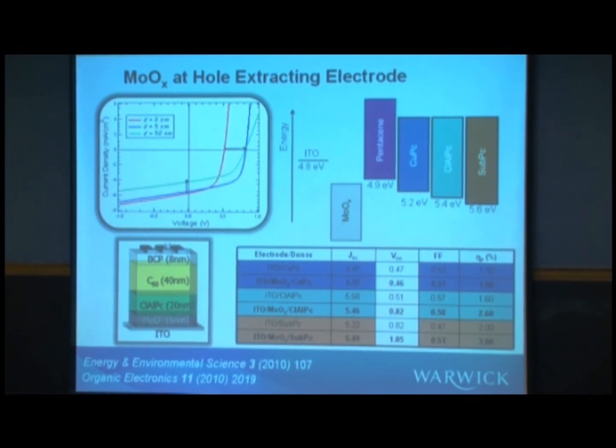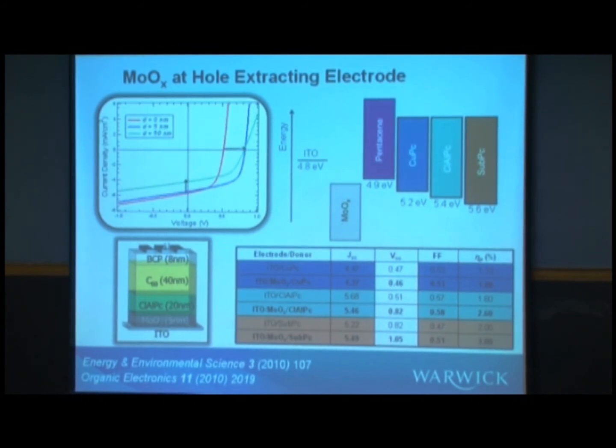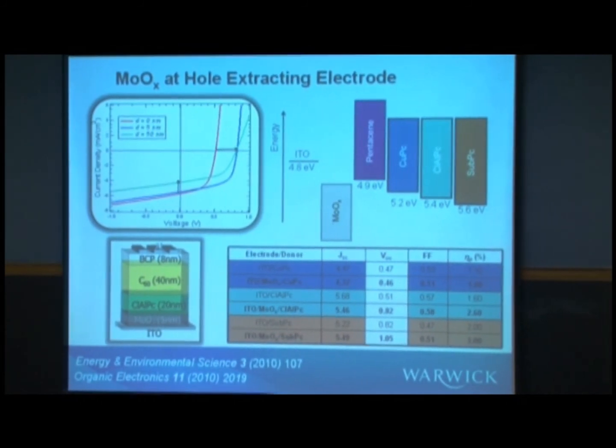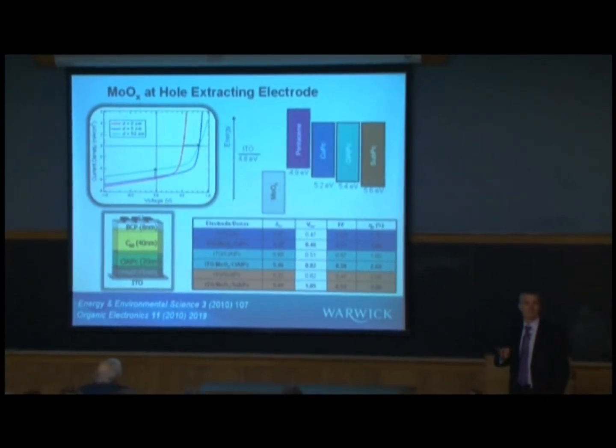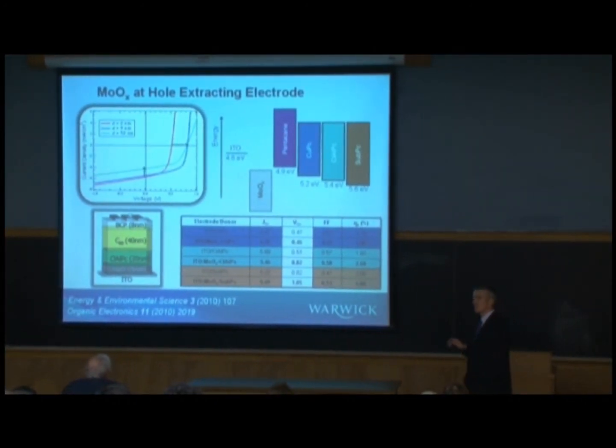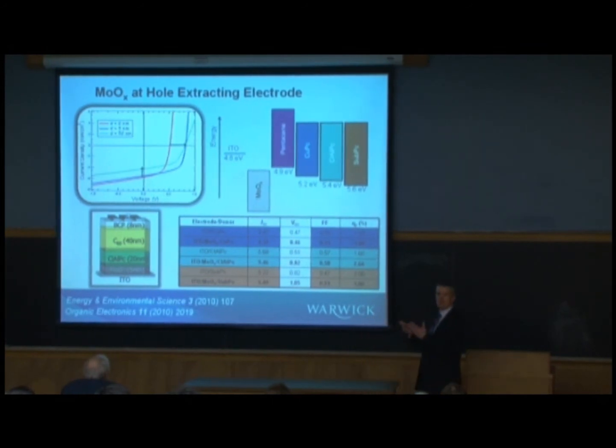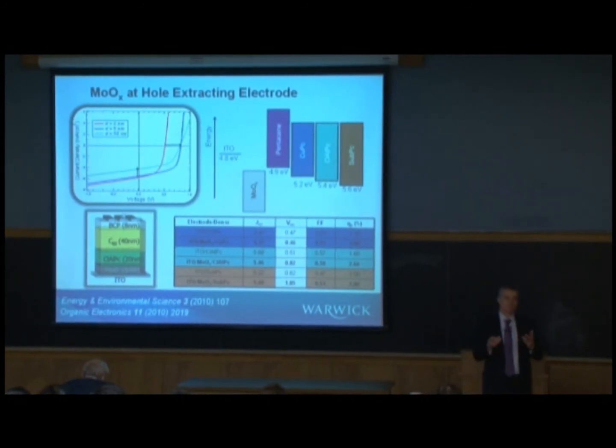There's a number of reasons why you want to do that. You want to extract the charges more efficiently, but also indium tin oxide is actually a very unstable material. So it's a big problem in the degradation of devices. It's not a very uniform material. You can buy ITO from the same manufacturer and it's got quite different properties.